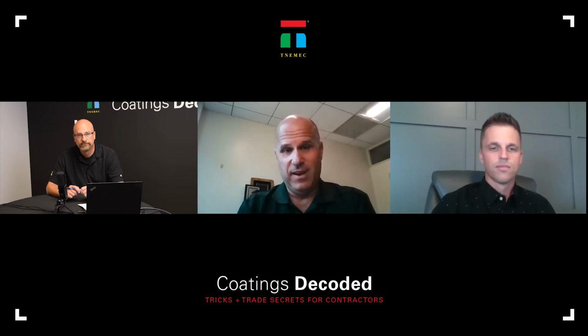Conversely, if I have a material that has a low thermal conductivity and can go on thicker, then I kind of have the best situation and I need fewer coats to get to a higher thermal benefit. So Andy, it sounds like for a contractor approaching an insulative coating project, the K-value of each product that might be considered and potentially quoted on that project is going to be really critical, because a lower K-value means a more efficient insulative product and potentially fewer coats than something at a higher K-value.